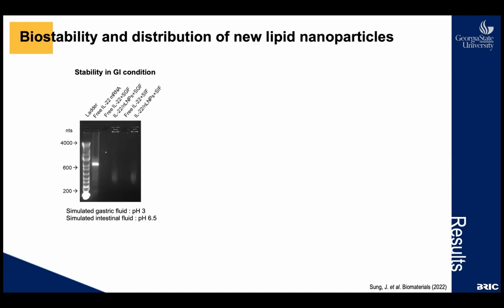Another important factor to check is the biodistribution and biostability. We exposed the free IL-22 mRNA and IL-22 lipid nanoparticle to harsh conditions similar to the GI tract. Samples were incubated with the simulated gastric fluid at pH 3 and the intestinal fluid at pH 6.5, then ran the electrophoresis to see how it's affected.